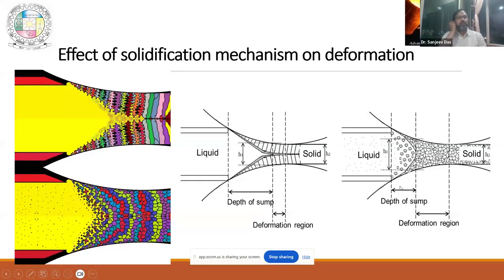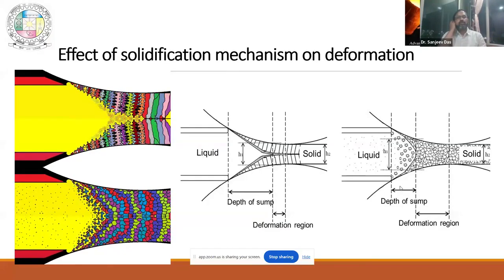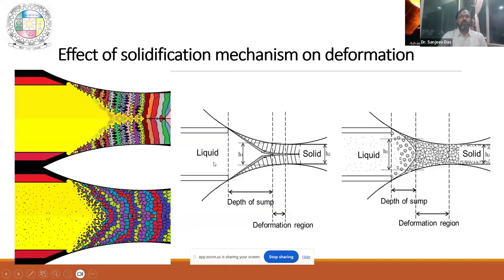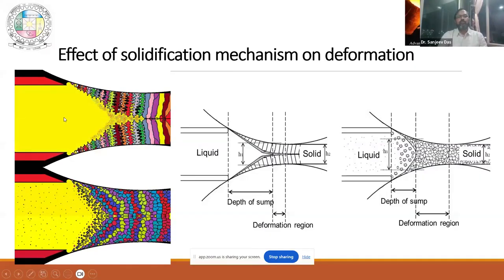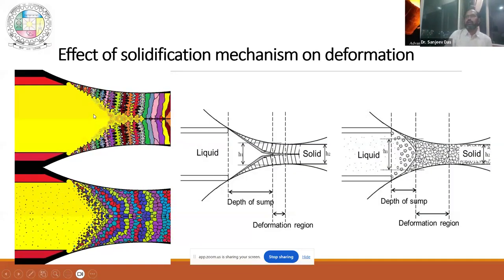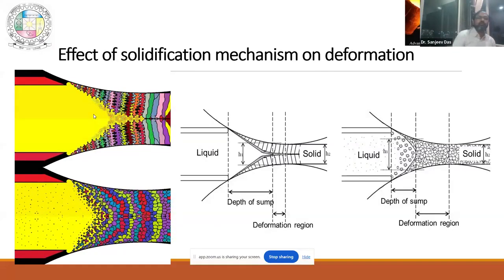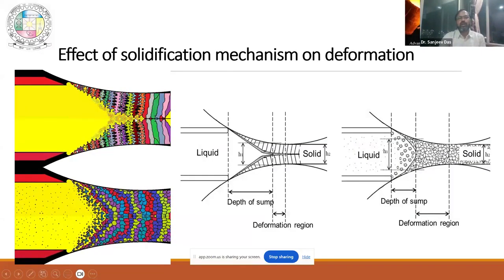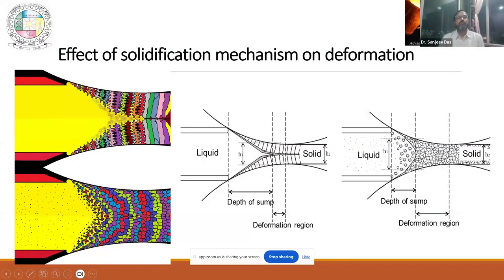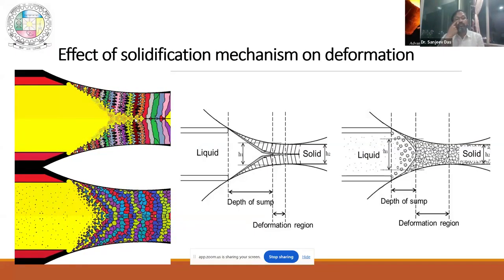So we came up with a theory of solidification, what exactly happens. These are two rolls which are rotating, and the liquid metal, the yellow part, is the liquid metal, and these are the solid which is growing from the surface. If there is no convection, the solid will grow from the surface to the interior. And when it happens, whatever you are adding inside it, any composite material or any alloying elements, everything will come at the center of the casting. Now, when it comes to the center of the casting, it drops down the melting point of that. That is understandable by the phase diagram.